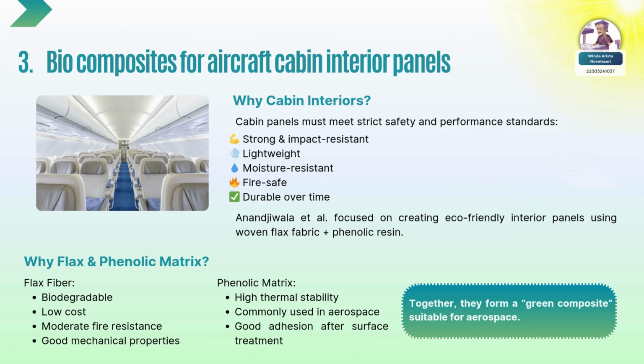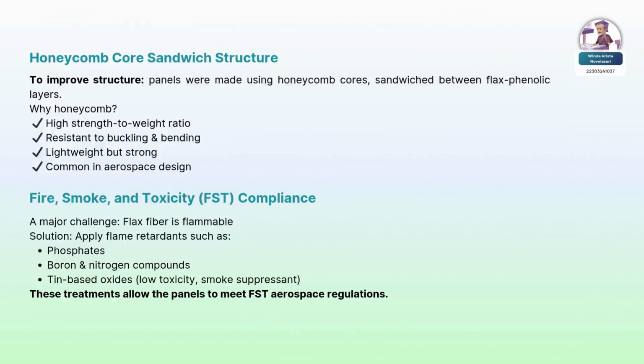Anandjiwala's team tackled all of this by using woven flax fabrics and a phenolic matrix. Flax is biodegradable and affordable, but it has only moderate fire resistance. Meanwhile, the phenolic matrix provides good adhesion and heat stability. Together, they make a strong candidate for an eco-friendly composite. To enhance performance further, they use a honeycomb core design, a technique already well known in aerospace. This structure makes a panel strong yet lightweight and also resistant to bending and buckling.